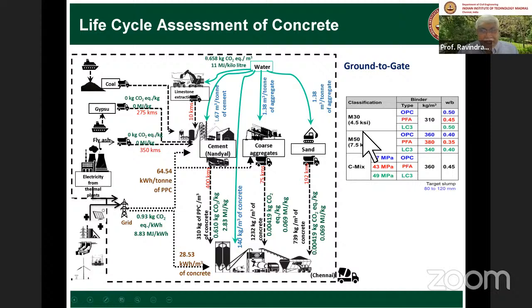I'll show you M30 concrete made with OPC, fly ash addition, and LC3. In this case, the M30 concrete required about 310 kg of the binder of the cement, and the water binder ratio was varied to get this strength. We also made a higher grade concrete, M50 concrete, with different binder contents needed for this M50 grade. And then there is a common mix which has the same binder content, but giving obviously different strengths because the binder is fixed here. In all these cases, the slump was about 100 mm. So these are workable concretes.